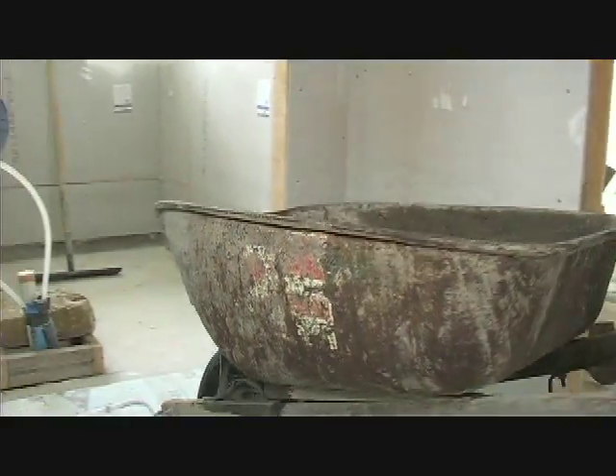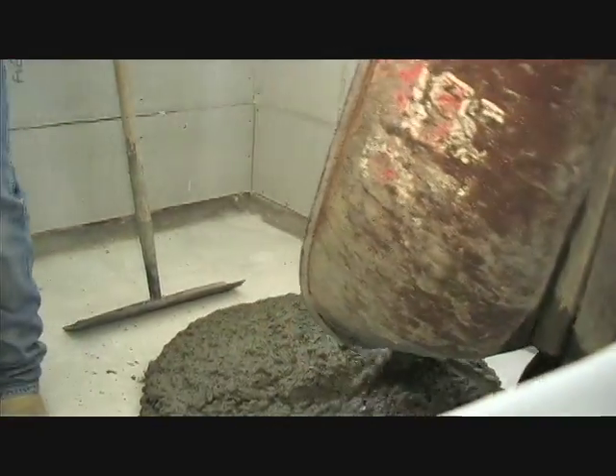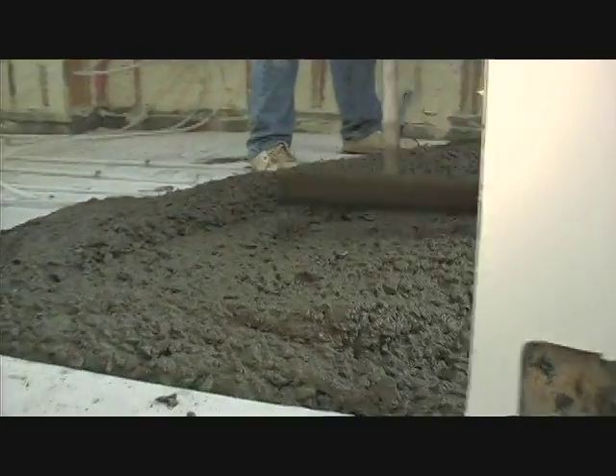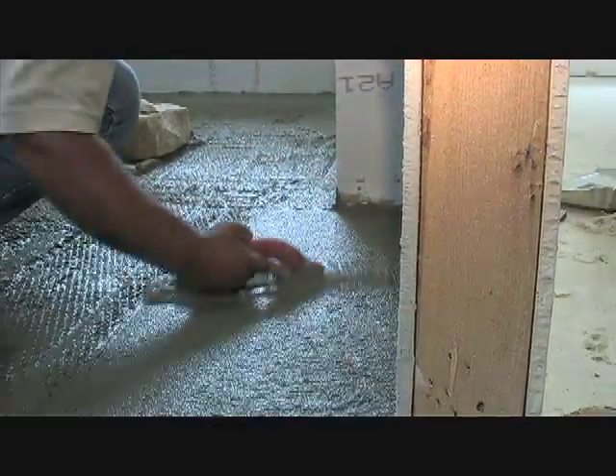We're pouring the floor in the bathroom today where our hydronic systems are. This particular floor doesn't really have a significant load or weight. If we were going to do flat work or a driveway with more substance to it, would you use the same material? Over the hydronic floor, you're pouring a very thin layer — in a traditional sense, you literally couldn't put a piece of steel in the correct spot because you've got such a thin section of concrete. These fibers work beautifully in a thin section to create tensile reinforcement where you almost couldn't fit in a piece of steel.